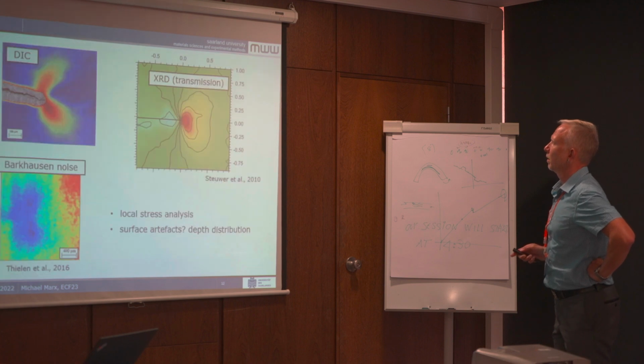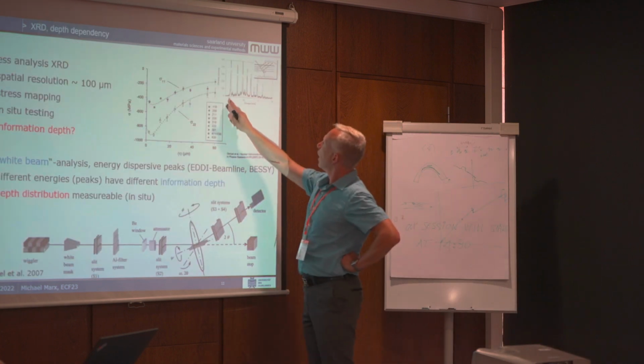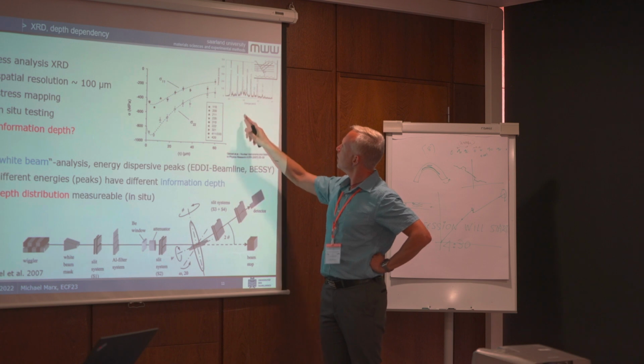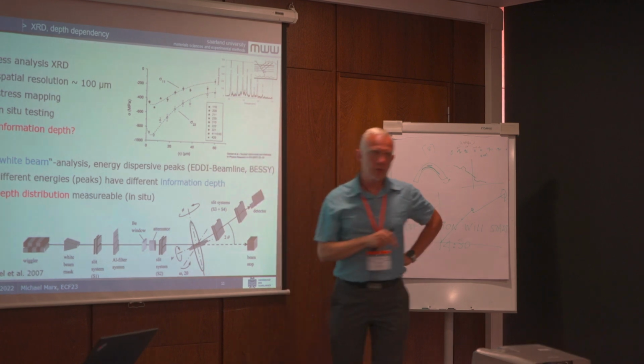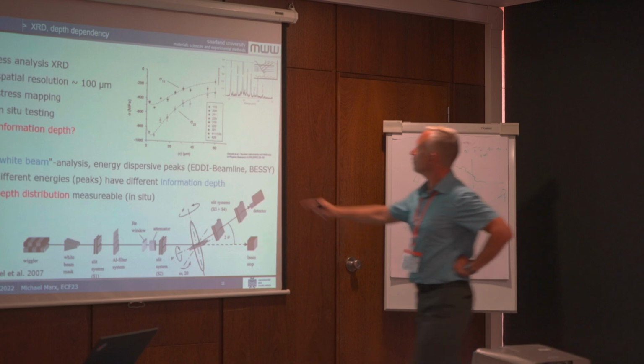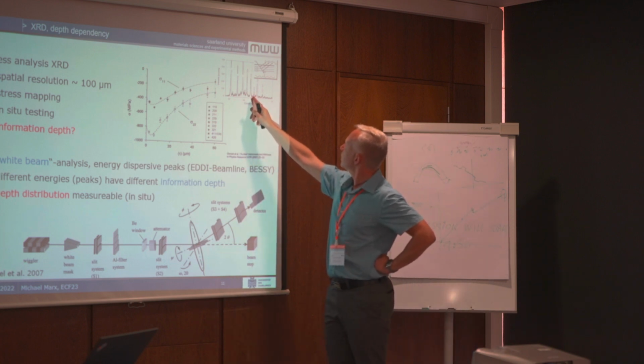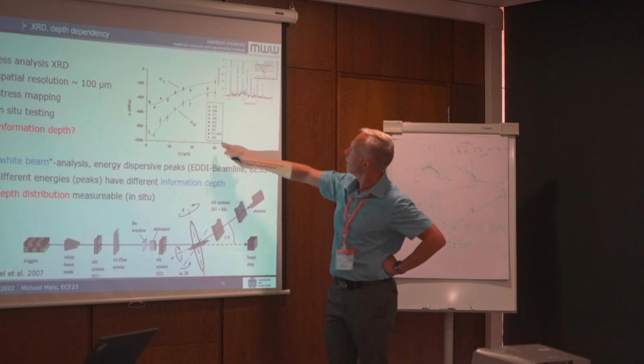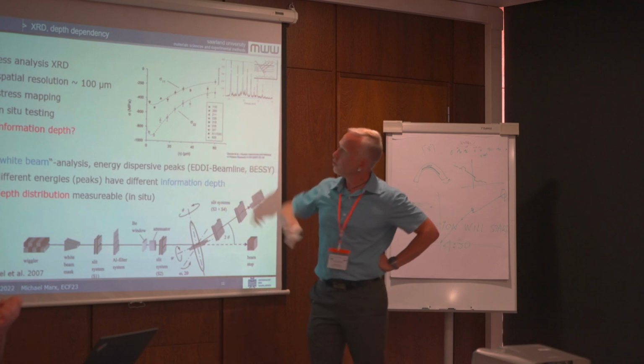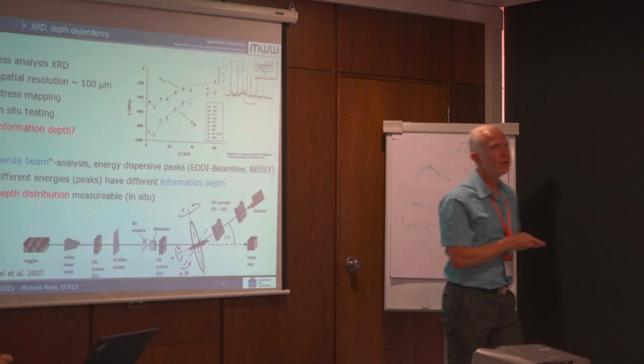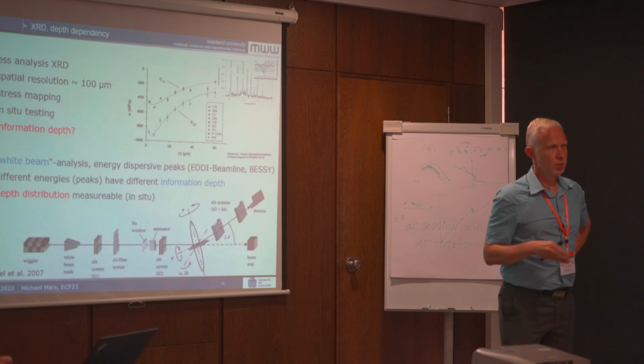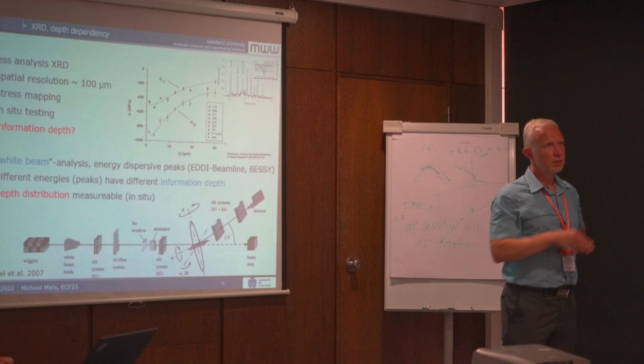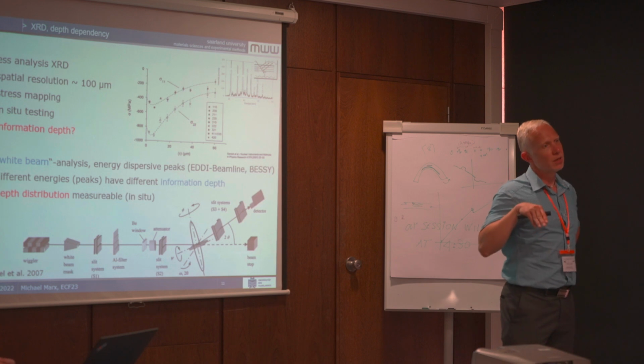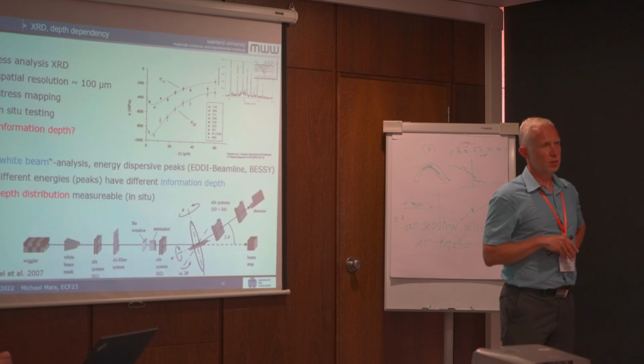Yeah. If you have your different peaks, you find them at a different energy. And if you have the peak 222, for instance, here at this high energy, then the information depth is higher than for the lower energy because of the absorption of the X-ray. So the X-rays at the higher energy can go deeper inside your specimen. Okay, so you've basically measured once, but you've got different depths from each peak. Okay. Thank you.